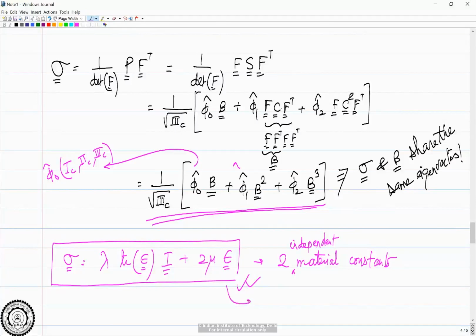So this thing here is for linear stress-strain relation, because that's what we do in undergraduate course. So when we say two constants, it is only when you have linearly isotropic material, whereas this is non-linearly isotropic, most general. And it can have infinite constants.